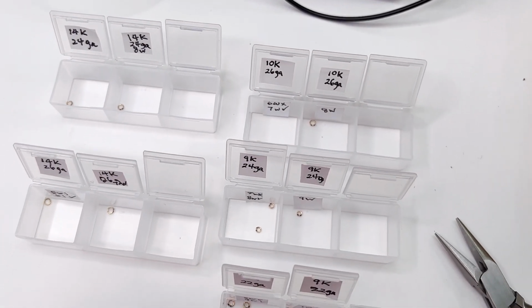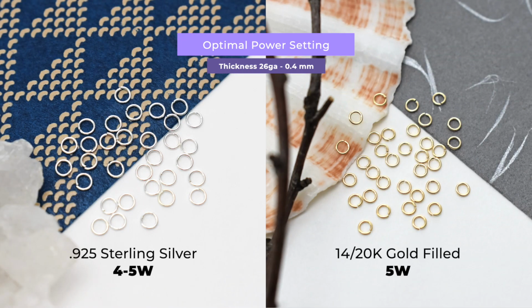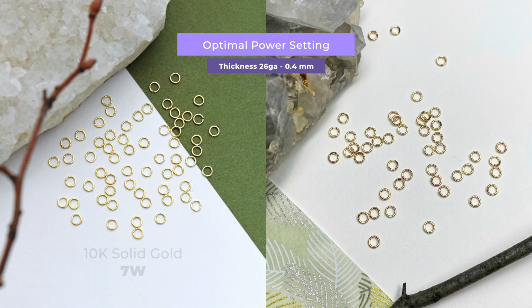For example, for 26 gauge, which is 0.4 millimeters, a single secure weld can be achieved for silver at 4 to 5 watts. Both of them did not flat top. And for gold filled, the best is at 5 watts. 14 karat solid gold is at 6 watts, and 10 karat gold at 7 watts.